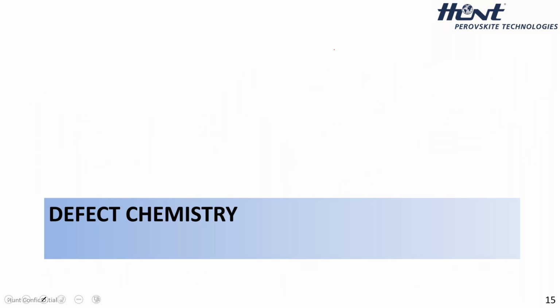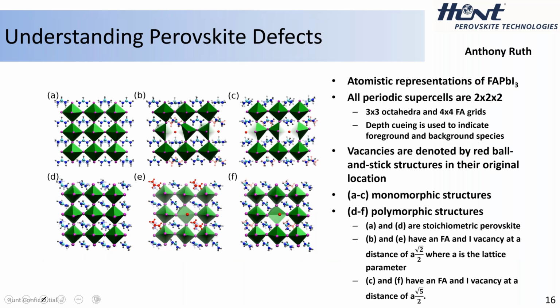So defect chemistry. Our defect chemistry approaches, there are several. Today, I will only focus in on density functional theory. And so we have some atomistic representations here of perovskite. Those along the top are monomorphic, meaning that you add a defect and you maintain the cubic structure. So everything's at 90 degrees. A is equal to B is equal to C. And then we have polymorphic. So you add the defect going from D to E to F. And then we allow the structure to relax or undergo polymorphism. And this is really important. And so the energetics of a monomorphic defect versus the energetics of a polymorphic defect will be highlighted in the slides to follow.